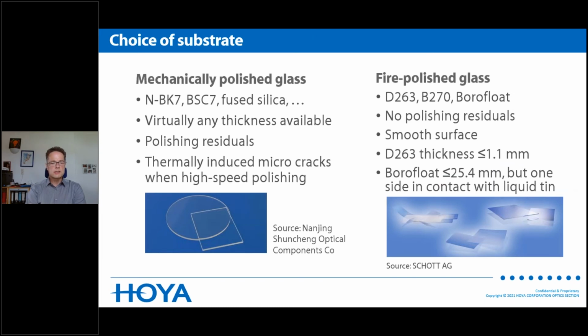The more complex the filters become, the more important the choice of the substrate becomes for the quality of the filters. For many, many years, the standard, and still is, are mechanically polished glasses. They can be BK7 or equivalent, fused silica, or many other glasses. The advantage is that you can have them in virtually any thickness.